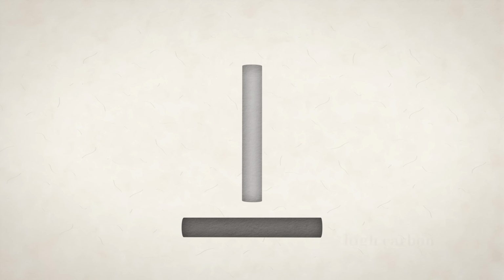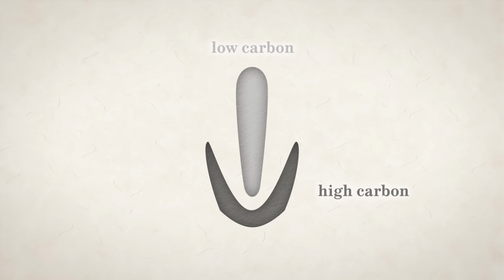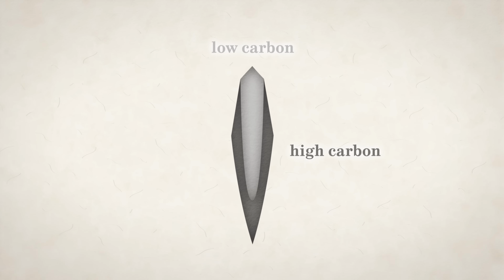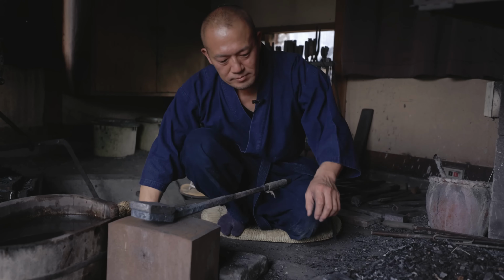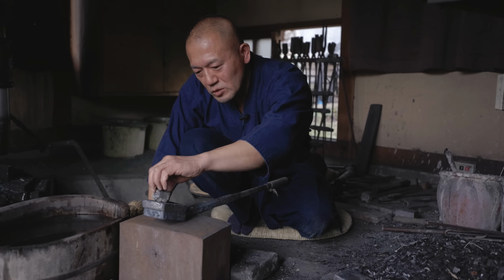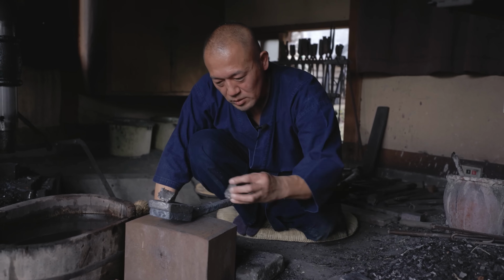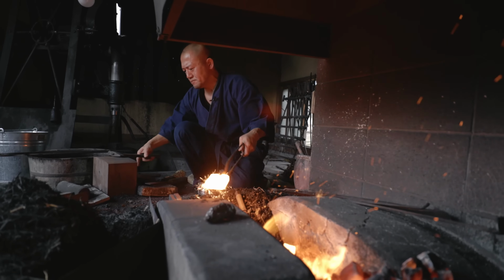The edge is always high carbon steel to make it hard and rigid so it can maintain a sharp edge for a long time, but the spine is usually made of lower carbon steel, which allows the sword to flex without breaking. This is done by welding together pieces of steel with different carbon contents.